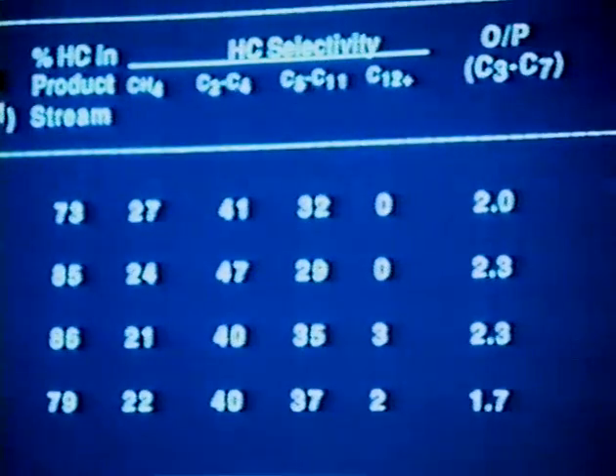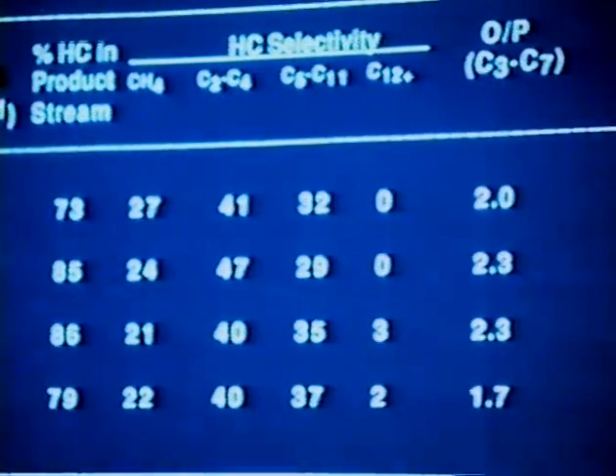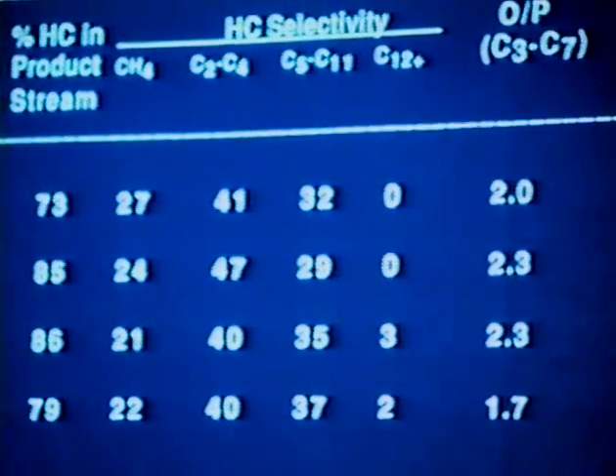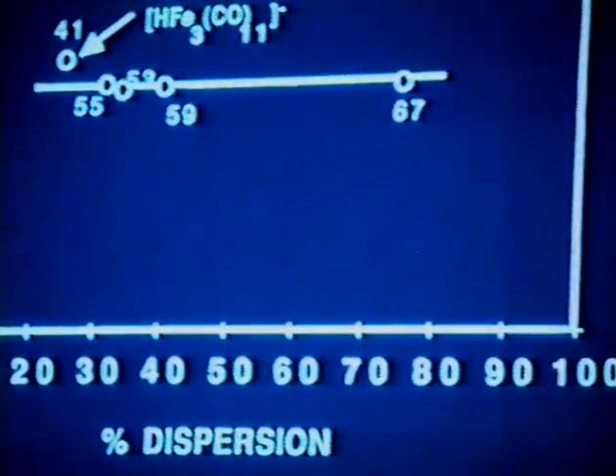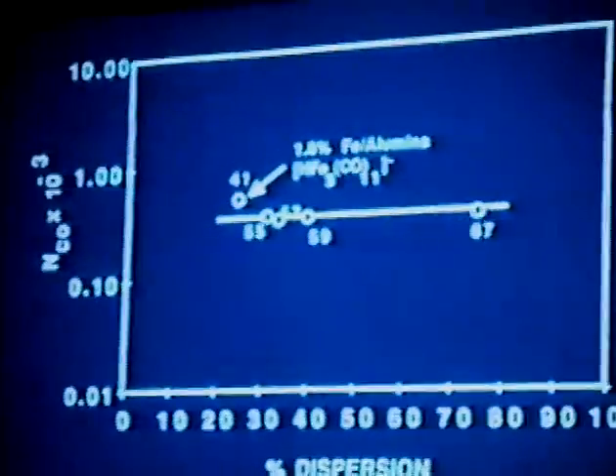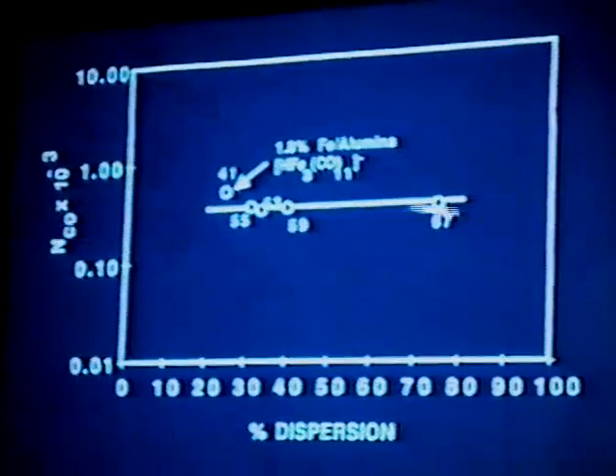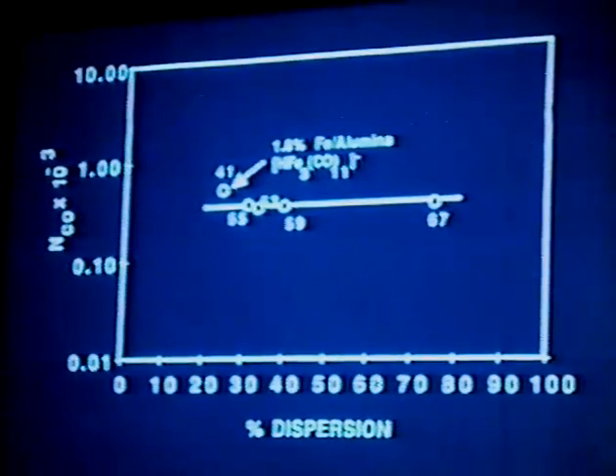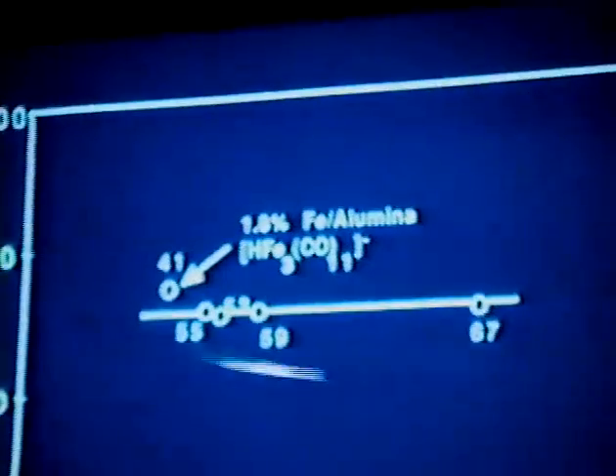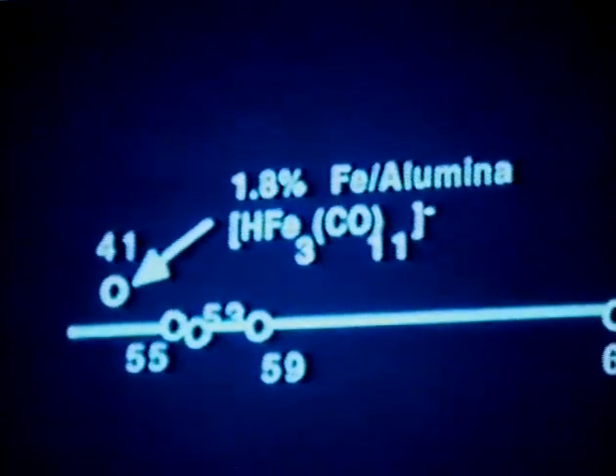This is contrary to the observation for supported metal catalysts, where you find a wide variety of changes in activity and selectivity properties with changing dispersion. Now, on a typical plot of structure sensitivity, if we look at it this way, we would conclude that the CO hydrogenation on this set of catalysts is probably structure insensitive.